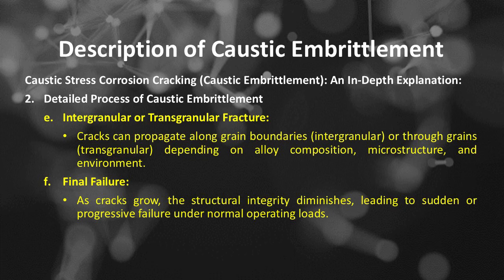Process of caustic embrittlement. Number E, intergranular or transgranular fracture. Cracks can propagate along grain boundaries, intergranular, or through grains, transgranular, depending on alloy composition, microstructure, and environment. Process of caustic embrittlement. Number F, final failure. As cracks grow, the structural integrity diminishes, leading to sudden or progressive failure under normal operating loads.